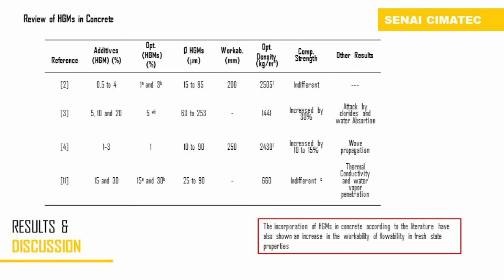Three important things you can see here are the range of percentage of HGM used as an additive, from 0.4% to 50%, the variability of diameter of HGM in these researches, and the impact on the mechanical and physical performance of concrete. For example, author three found an increase of 30% in compressive strength, and other authors also found an increase of 10 to 15% with optimal workability results. Another important thing is that the incorporation of HGM in concrete, according to the literature, has also shown an increase in workability and flowability in fresh state properties.